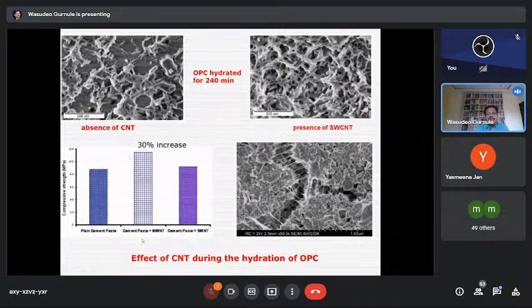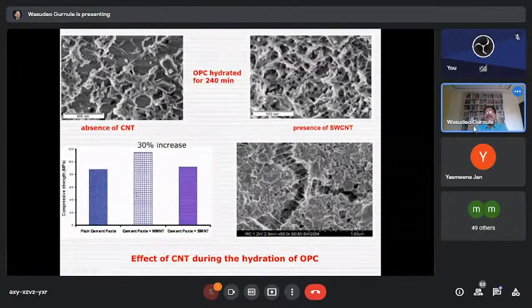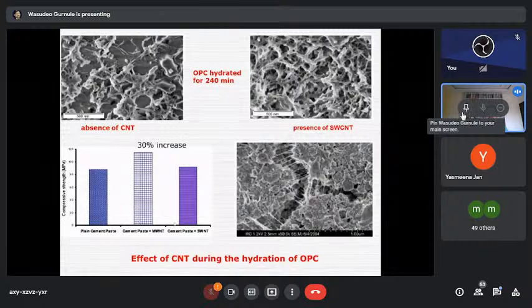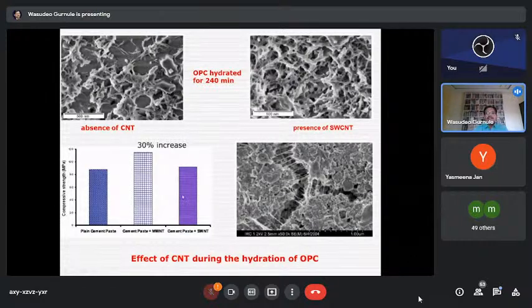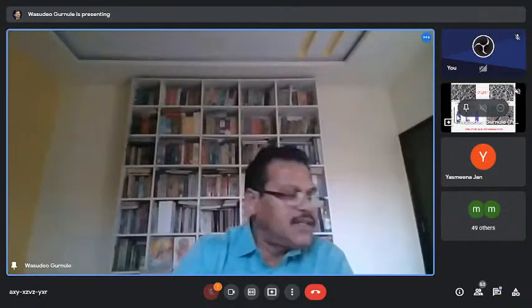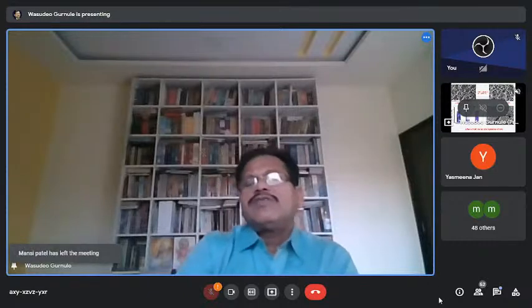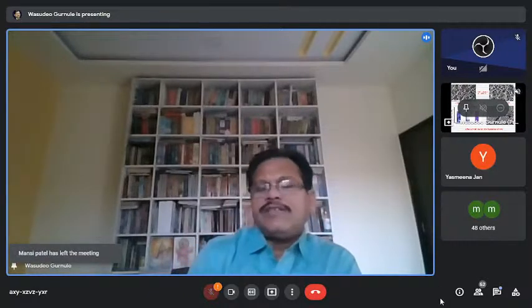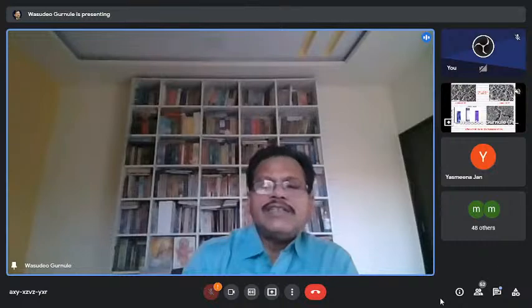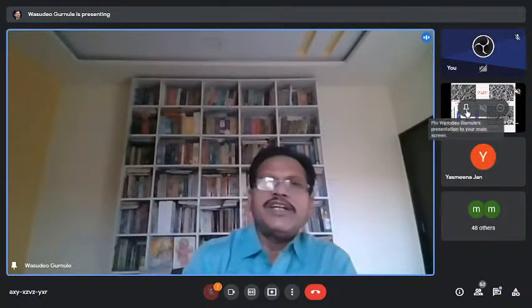And it is also observed that when we mix multi-walled CNTs with the cement paste, the strength and efficiency of the cement increases by 30%. And if you use single walled, there is a slight increase, not much more. But as compared to plain cement, we can increase the efficiency in terms of strength and durability. So this is one of the experiments shown here, that it increases the efficiency by addition of CNT.